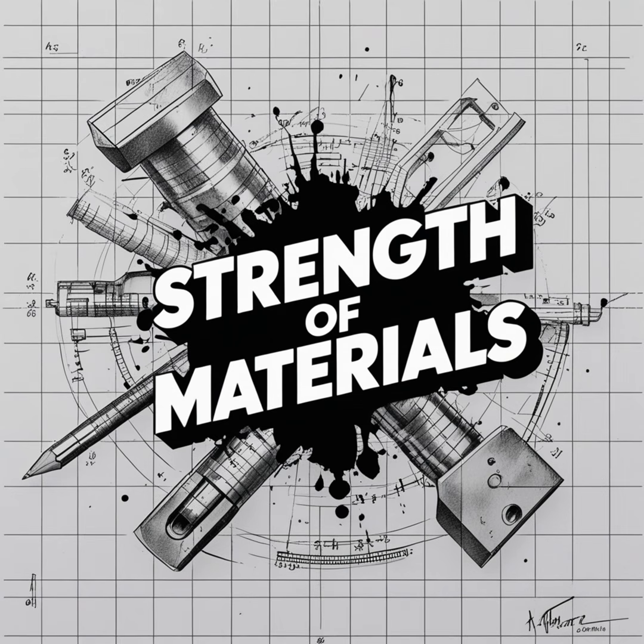You've got it perfectly. So we have two competing universes. Basquin rules the high cycle universe, governed by the strength of the metal. Coffin-Manson rules the low cycle universe, governed by the ductility of the metal. How do engineers bridge the gap? Through the strain life general approach, it's wonderfully logical. Total physical strain is simply the sum of elastic strain plus plastic strain. Makes sense. So the total strain amplitude equation just combines the two. The elastic portion, governed by Basquin, added to the plastic portion, governed by Coffin-Manson.